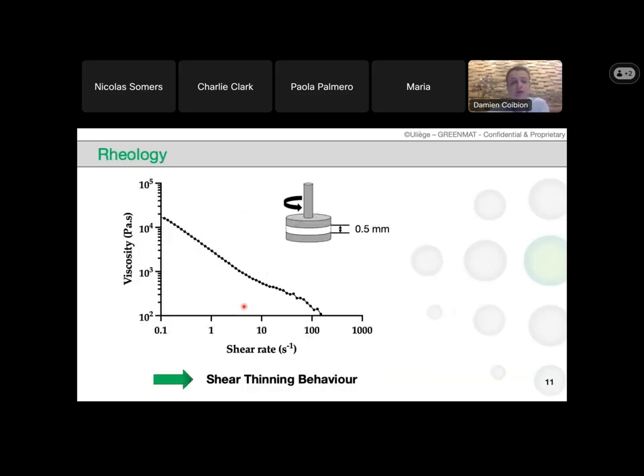And at this stage, we have to see if our paste has the good rheological behavior. To do that, we put a little paste inside the rheometer between 2 plates. The bottom one is fixed and the upper one is rotating. And during the rotation, which is increasing, we will have a look at the viscosity. As you can see, at the quite steady state, we have a very high viscosity. And when we are increasing the rotation and that increases the shear rate, we can see that the viscosity is decreasing. So we found the shear thinning behavior required to have a good spreading of the paste inside the 3D printer.